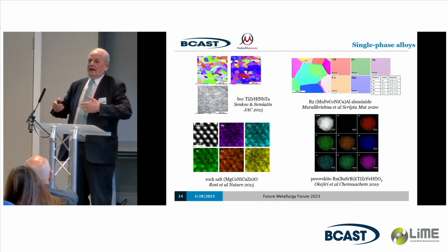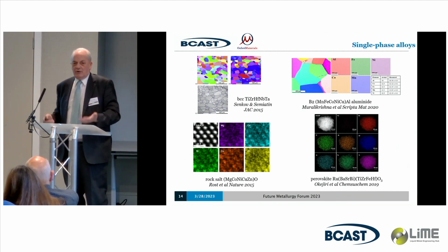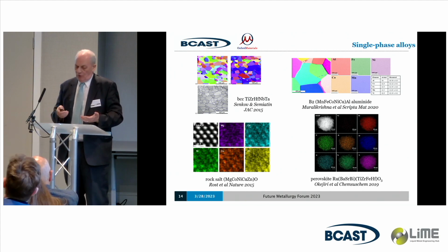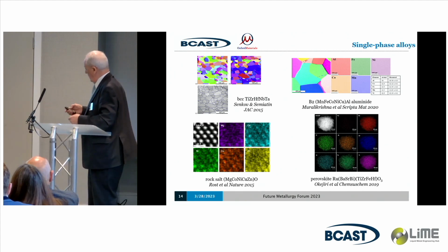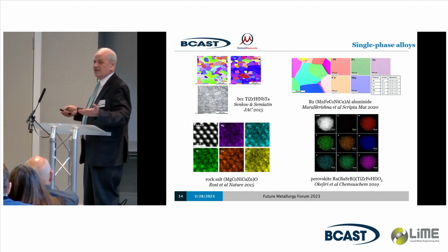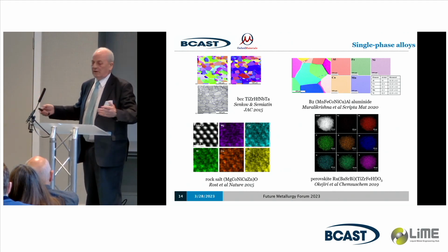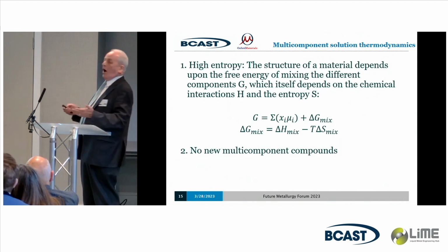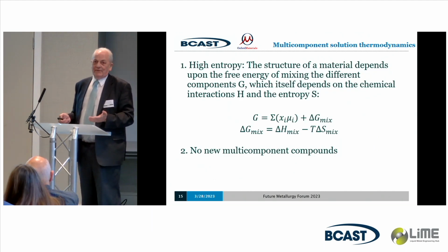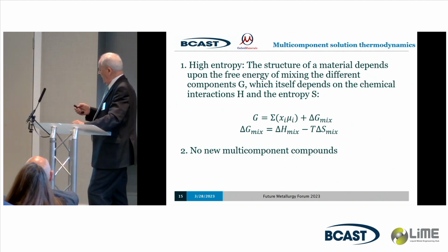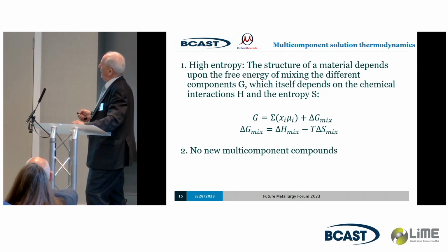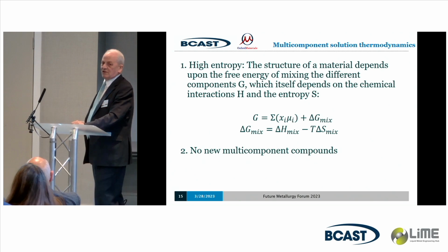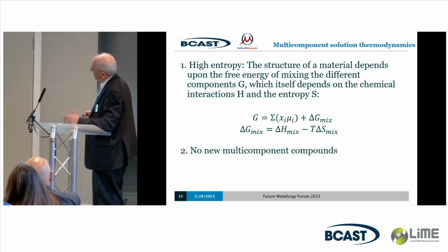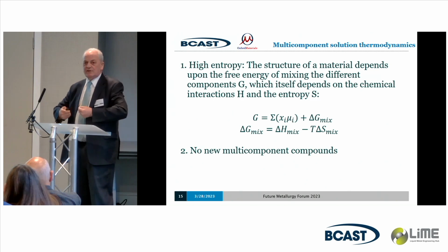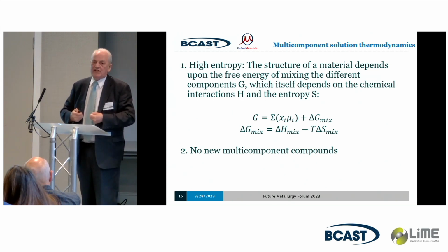You pick almost any crystal structure we know of in our binary and ternary world, and when you go into multi-component phase space, you find that there's an enormous single-phase region of each of them, all of them. Now the why? Well, it's actually not very difficult to understand, and we knew it almost at the beginning. The main reason, and it's why they're called high-entropy alloys. The structure of material depends upon the free energy of mixing, and the free energy of mixing, when you start to alloy, is dominated by the enthalpy, or basically the energy of interaction between the atoms, and that's a compound-forming tendency in most cases.